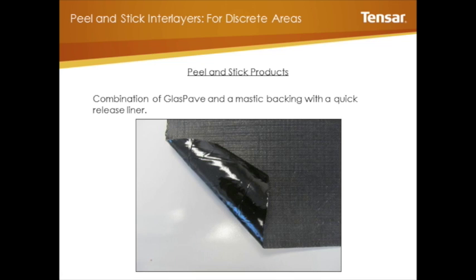Remember, a lot of these materials require a tack coat for installation. So you have to come down with your distributor and spray tack on the road surface before you install your product. And that's quite a lengthy exercise. So it lends itself to larger application areas. Where you have just a localized crack, you would like to just come in and, what I like to term it, a Band-Aid. You just want to install some material over an isolated crack here or there.